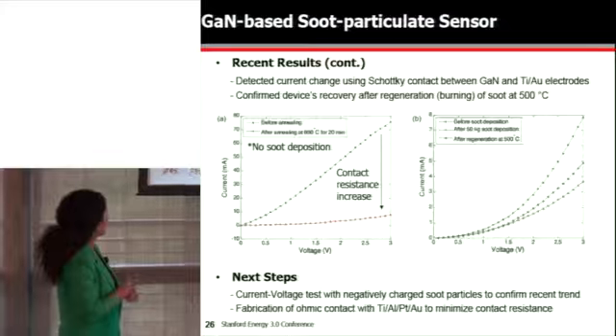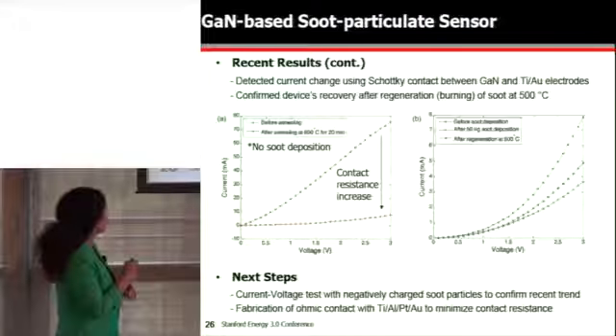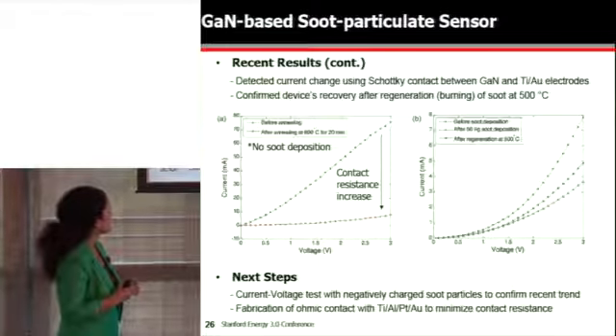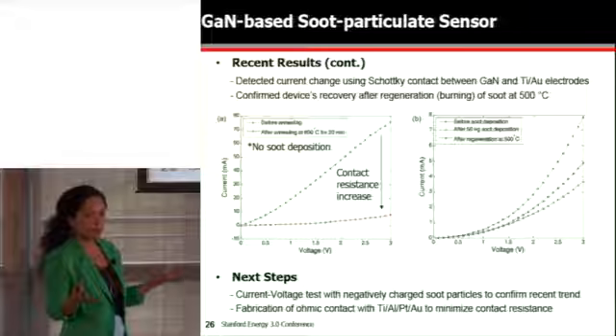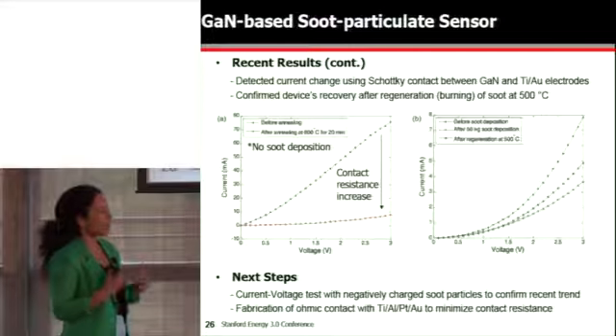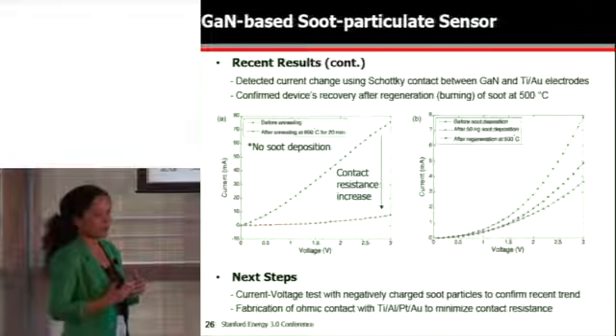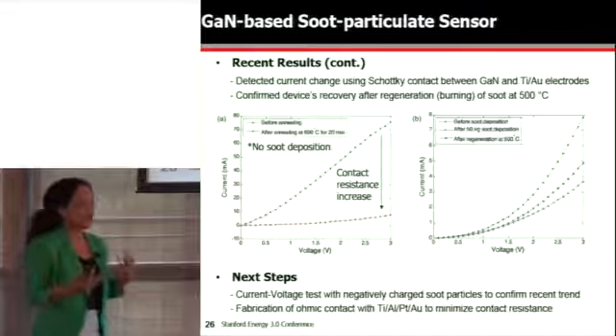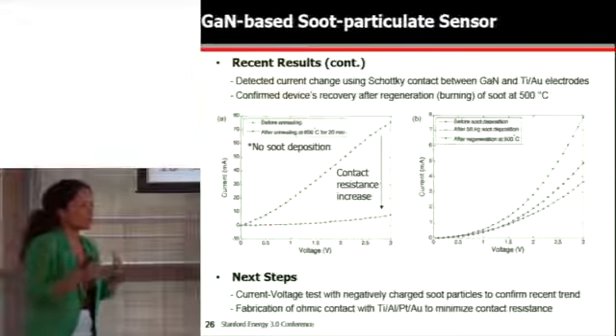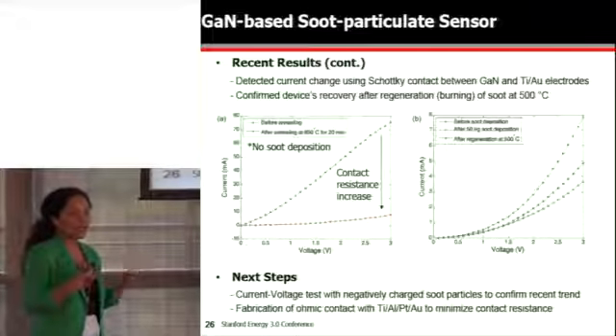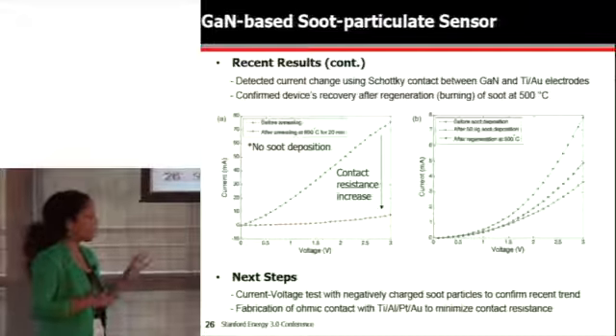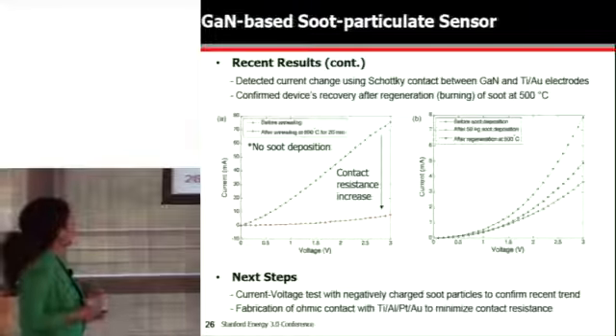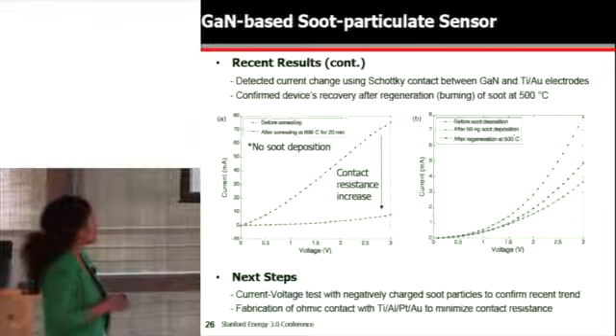This is just some data of our soot particulate sensor using gallium nitride. This is the current voltage response of the device with no soot deposition. The blue curve is showing the initial response of the device, and then the secondary response after we heat up the device to 600 degrees C. So when you're developing high temperature sensors, it's important to actually understand the impact of the temperature on your metal contacts to your semiconductor. So we often have to burn in our devices and anneal them so that the metal contacts are stable, because what's happening is your metal is starting to alloy with the semiconductor, and it's important to understand that. I haven't showed you any slides on that in this talk, but I'm happy to answer questions about that. But that's something we think about when we design these sensors.